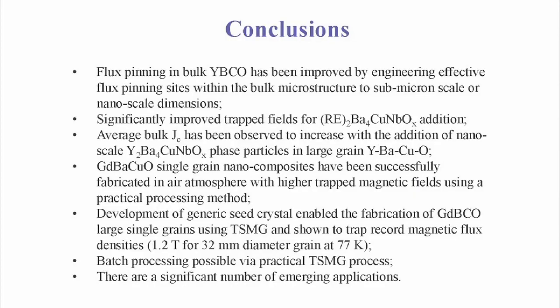Okay, so let me conclude. So I hope I've convinced you that bulk, rare earth, barium cuprate materials have got enormous potential for high field applications. They're very exciting. You have to be able to control flux pinning, but if you do that, you can improve the trapped field significantly by adding the right inclusions, in this case, 211 phase.